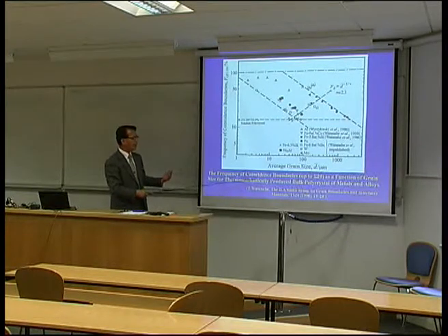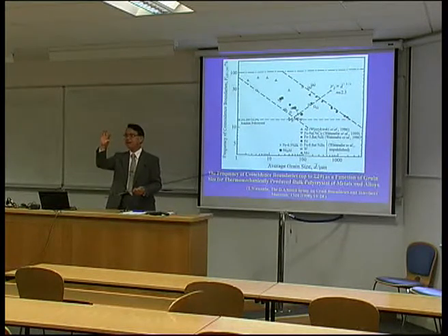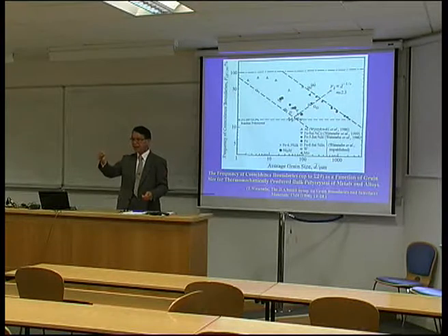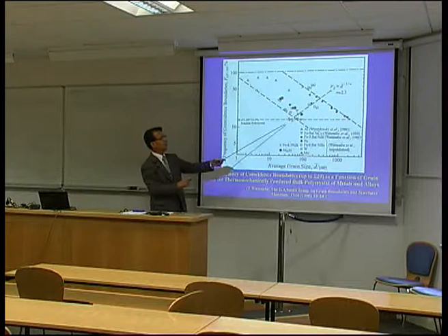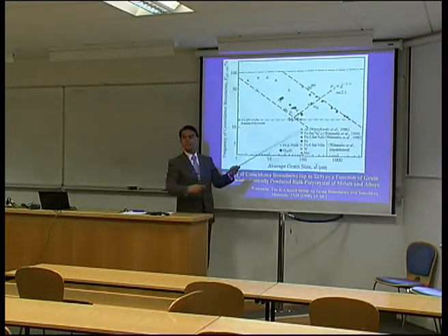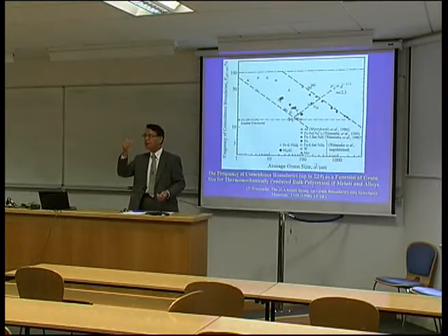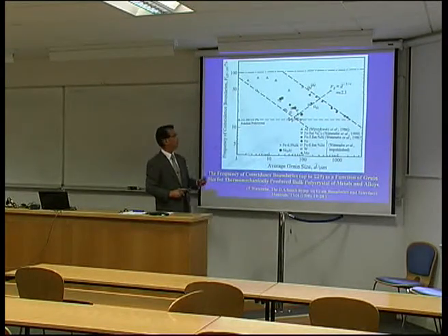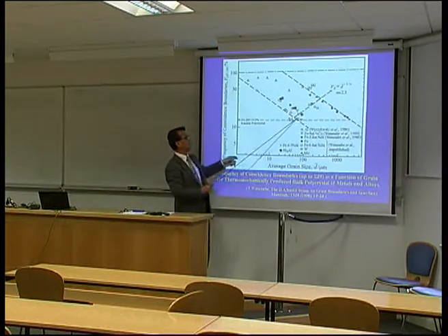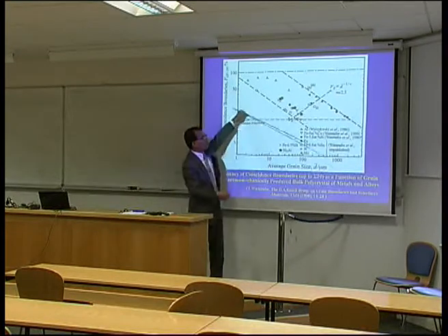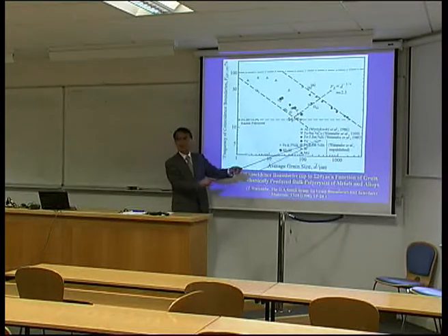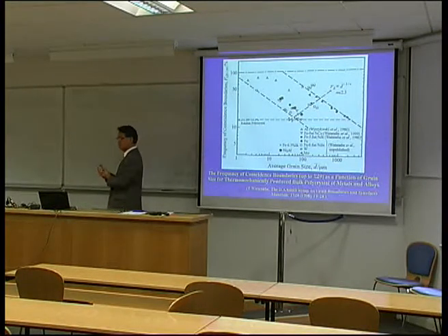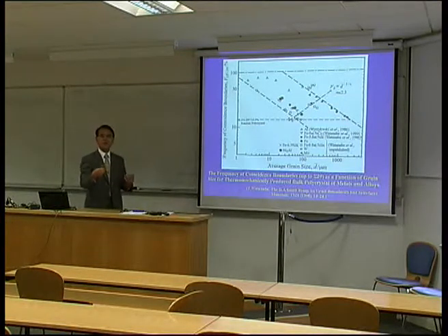But I want to emphasize, this is for rather thick, mechanically produced metallic samples. In the case of a polycrystal sample produced by other processing, for example iron silicon alloy produced by rapid solidification from the melt, so this is a very thin sample, with increasing grain size the fraction of low energy boundaries increases. So we observe quite the opposite tendency. Depending on the processing, even for the same material, the behavior is quite different. This is a very important finding, otherwise we cannot predict the bulk properties.